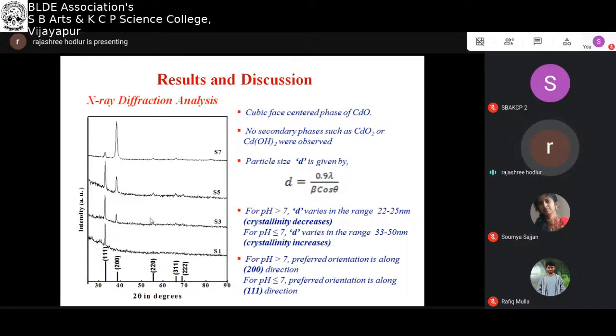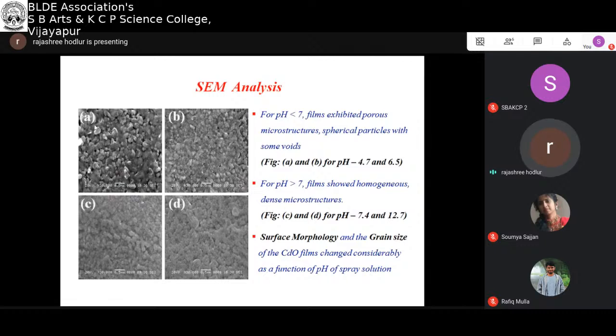So here for these cadmium oxide films, by varying the pH, we could tune its particle size, we could tune its electrical conductivity. So using SEM analysis, the particle size and the cluster formation also could be tuned in a controllable manner. So the surface morphology and the grain size of the cadmium oxide films changed considerably as a function of the pH of the spray solution.